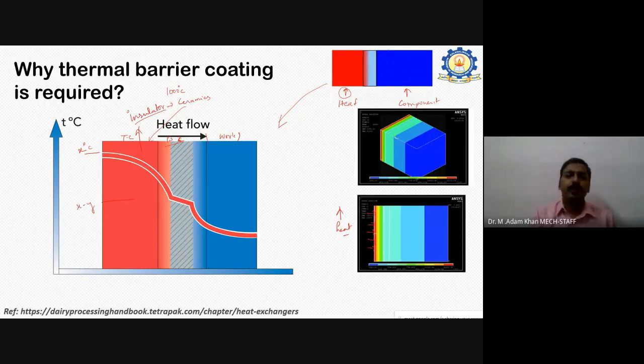And what is the bond coat used for? The bond coat relates to the work material, the base material, so that the sudden heat change of X minus Y need not touch it immediately. Some Z change can be different, so this may be X minus Y minus Z. For example, at this state it is 1000 degrees centigrade, and it may reduce here to 900 or 920 degrees centigrade. How has it been reduced?